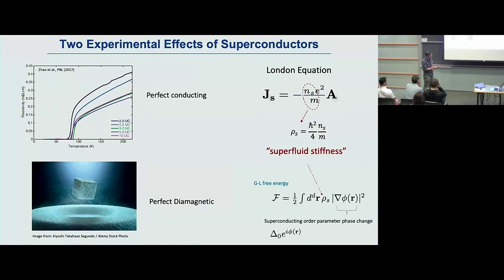The superfluid stiffness is defined as the coefficient connecting the free energy with changes of the superfluid order parameter phase, and that's where the name comes from. But the important part is that for any superfluid, the superfluid density divided by the constituent mass is proportional to this stiffness. In fact, by that definition, the superfluid stiffness has units of energy. We'll discuss the units a little later.